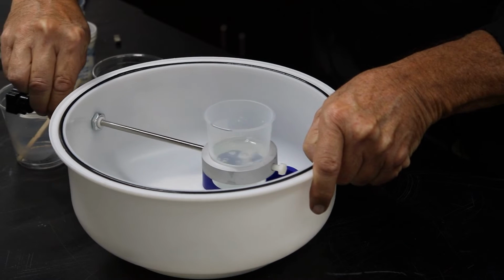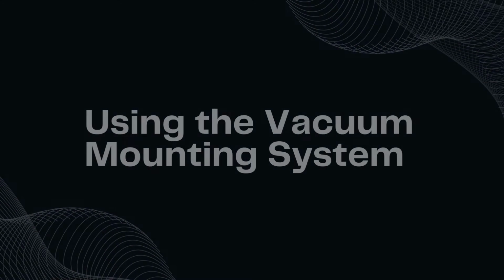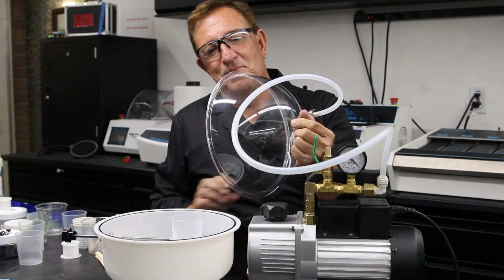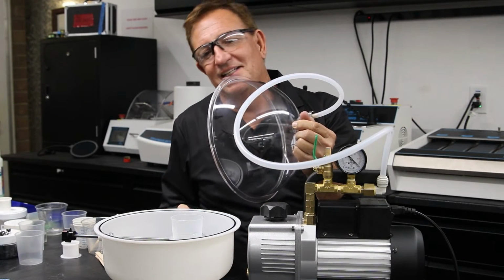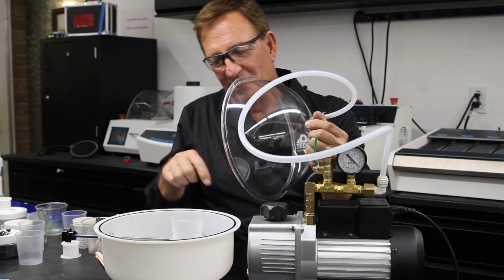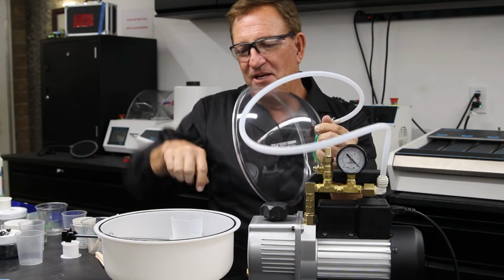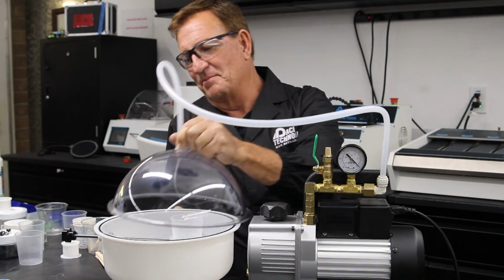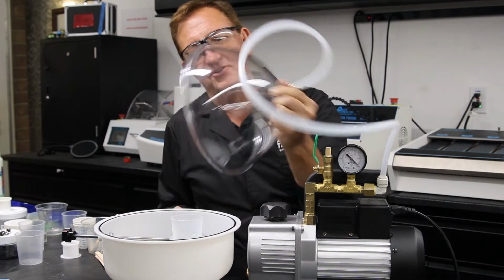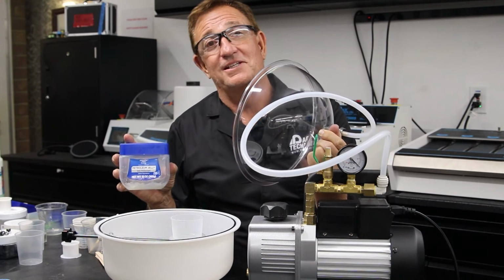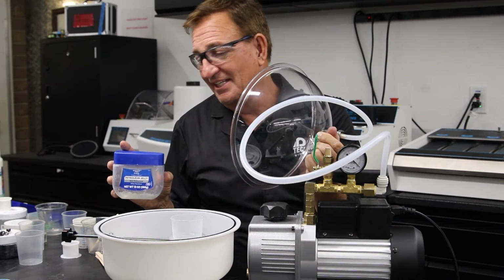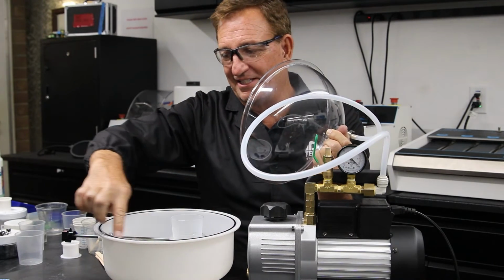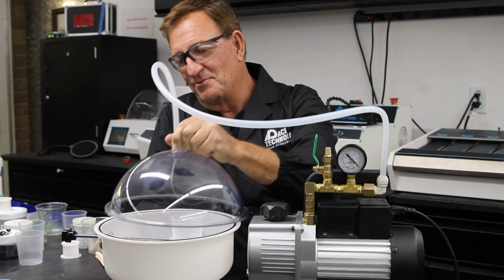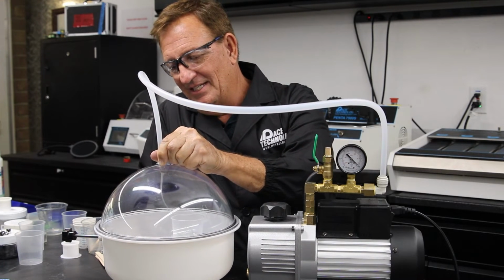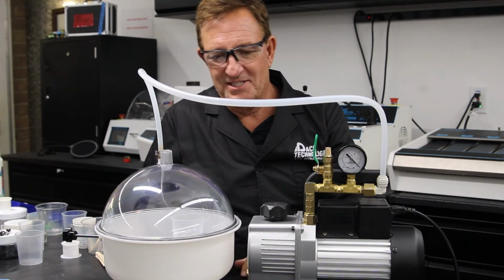So now what we want to do is pull the vacuum. At this point, we're ready to go ahead and pull the vacuum on the system. Now there is an O-ring on the lower chamber here that will help us have a little bit better seal. What I like to do is use a little bit of Vaseline or petroleum jelly to apply to the edge here, and that helps hold it down as well. Because you want to have a fairly good seal. And so we're all set there.